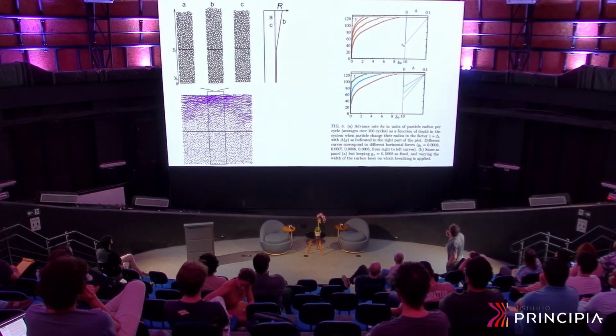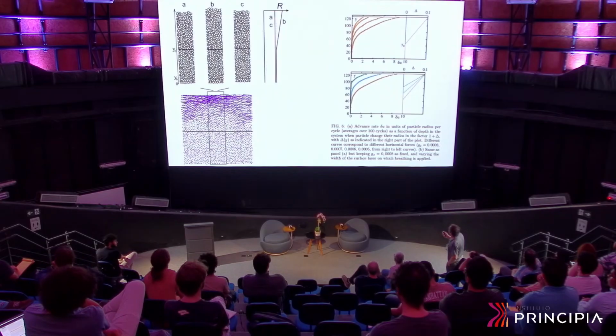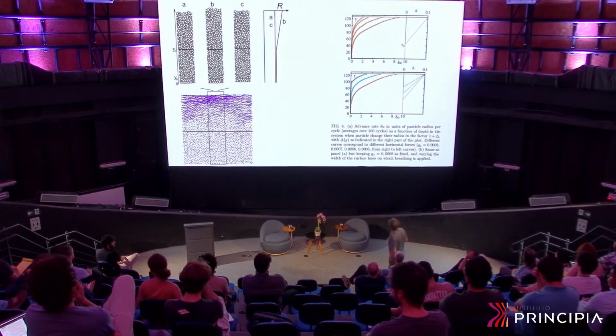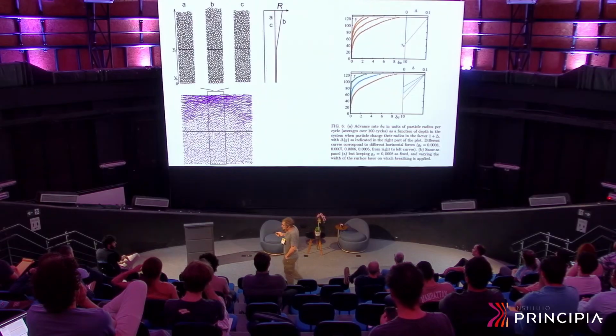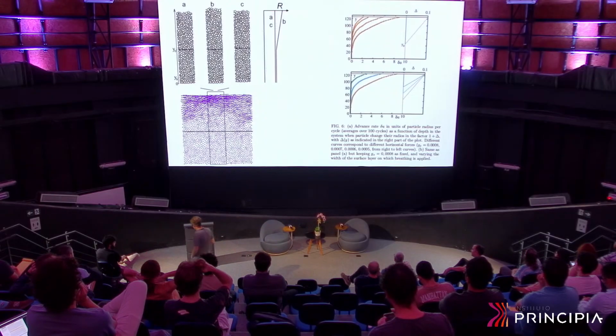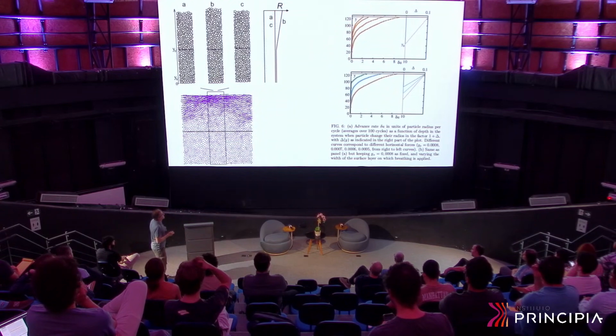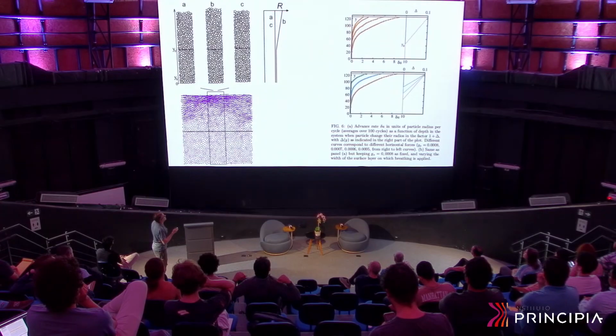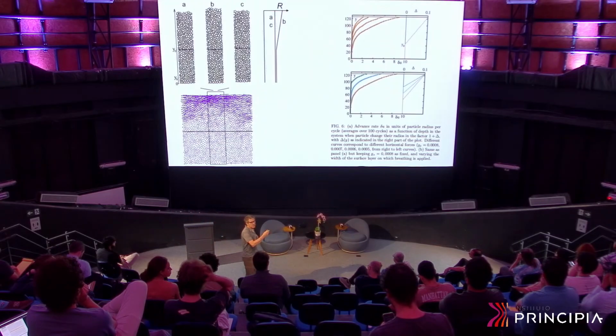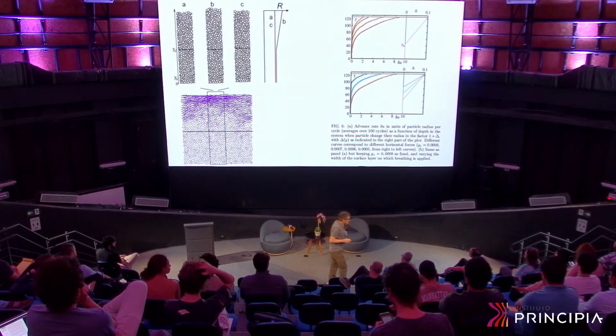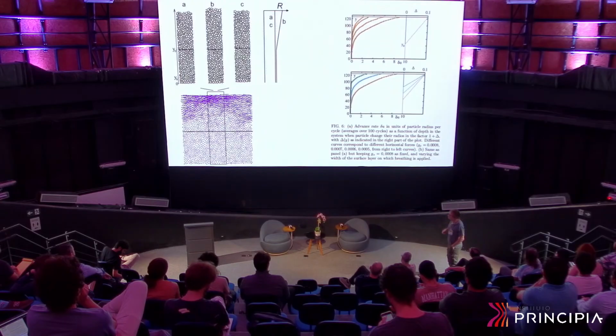And this is another case in which we take profiles of different forms like this, and we observe the profile of creep in the form of these three curves that are more or less exponential, as the experiments indicate they should be. But here there are a lot of unknowns in the problem. We take this very simple linear profile of temperature. One should probably put a more realistic profile obtained with the equation giving the temperature as a function of depth, etc. But we didn't go into much of those details.